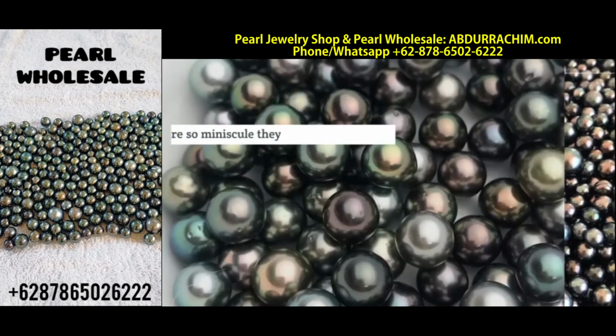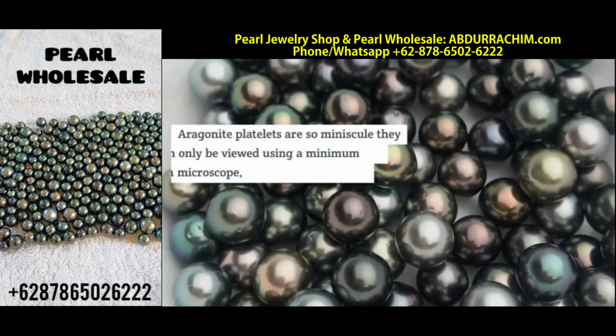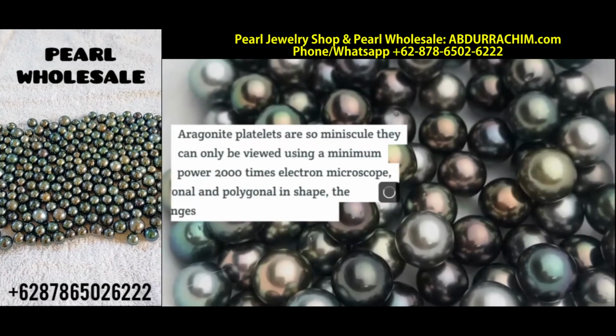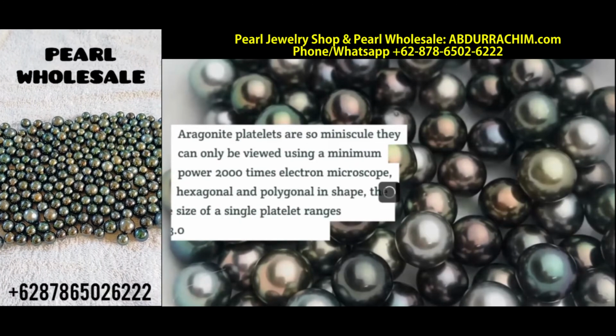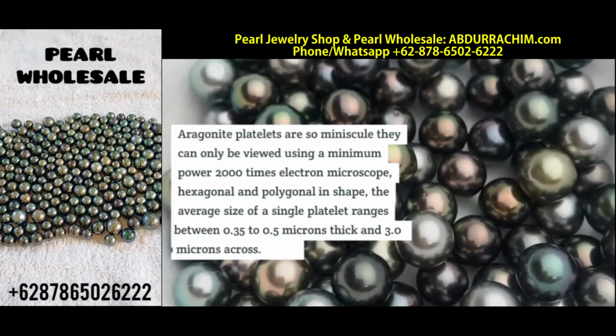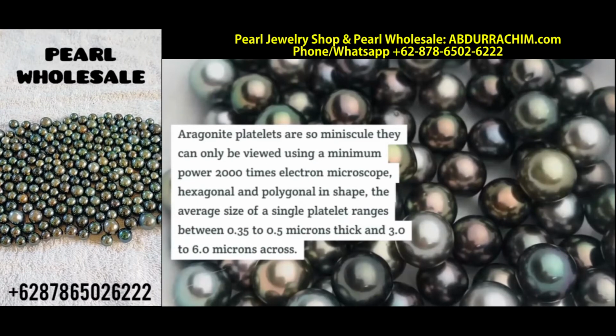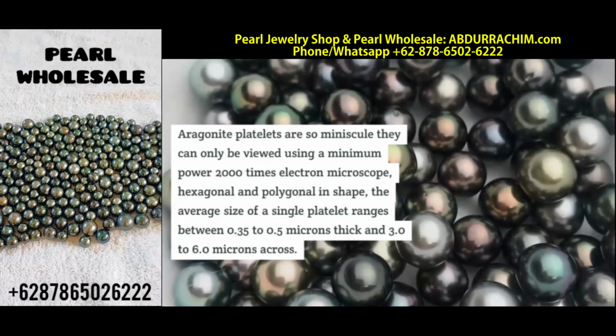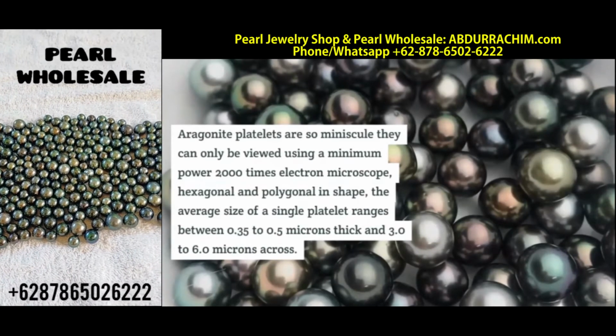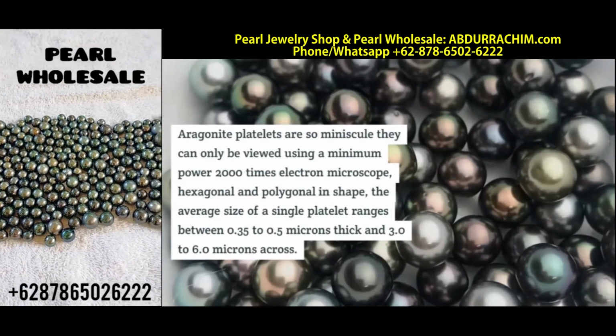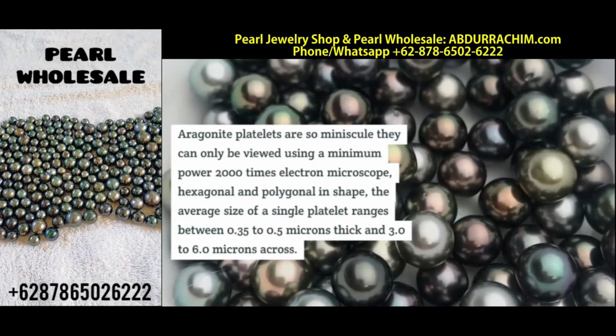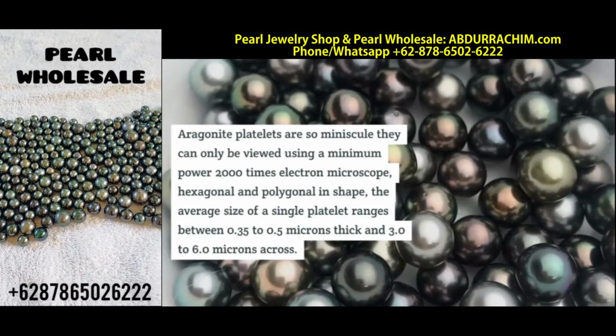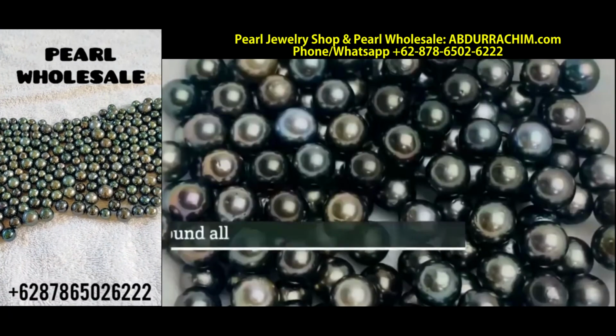Aragonite platelets are so minuscule they can only be viewed using a minimum 2000 times power electron microscope, hexagonal and polygonal in shape. The average size of a single platelet ranges between 0.35 to 0.5 microns thick and 3.0 to 6.0 microns across.